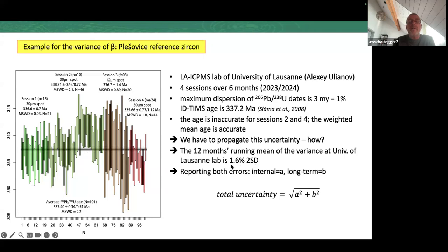And this uncertainty we now have to propagate on our total uncertainty in this way. So the best is that we report 2 errors when we give a laser ablation age. The internal one from data scatter alone, and then the integrated one, the long-term, adding the long-term uncertainty calculated in this way.